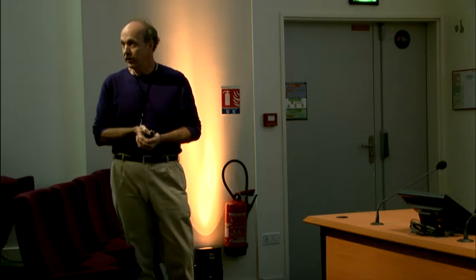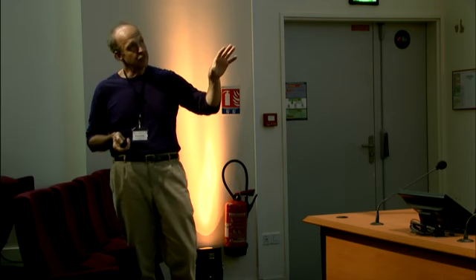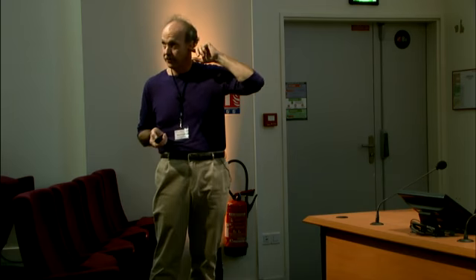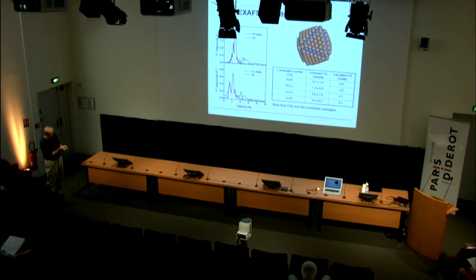The main thing that's useful that can be extracted from XAFS for the types of experiments we do is the coordination number. For example, for the platinum edge, if we look down at this table for the platinum-platinum coordination number, the coordination number is, on average, how many platinum atoms are next to every other platinum atom. If you imagine, this blue sphere here is platinum. This is on an edge, so it really only has 2 or 3 nearest neighbors in its first coordination shell. So its coordination number might be 3. But buried down in the middle of this particle is another platinum atom, and it has 12 nearest neighbors.